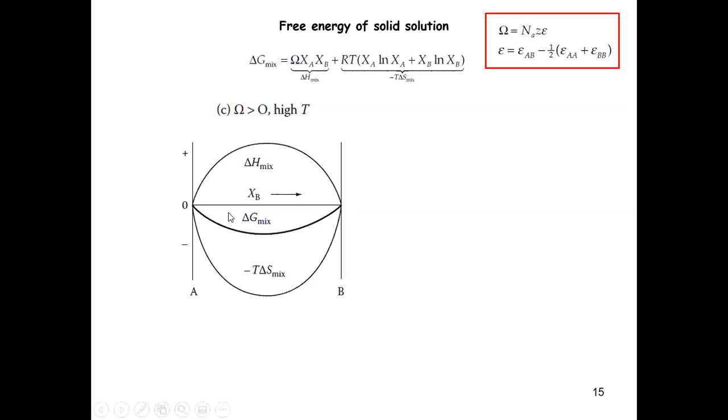Right, so we add these two together, and because the entropy contribution is so negative, the overall free energy, delta G mix, is still going to be negative for all compositions. Does that make sense to everyone? Okay. But depending on the very high value of omega, if that omega curve is even higher, and if the temperature is not that high but still high enough...